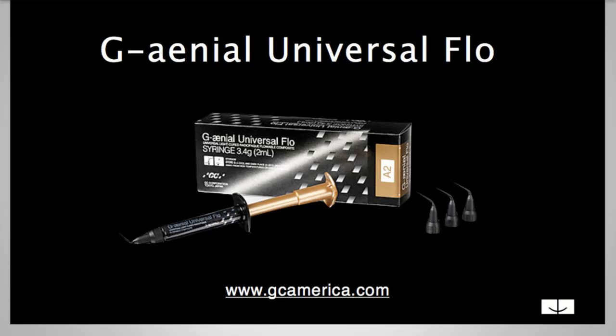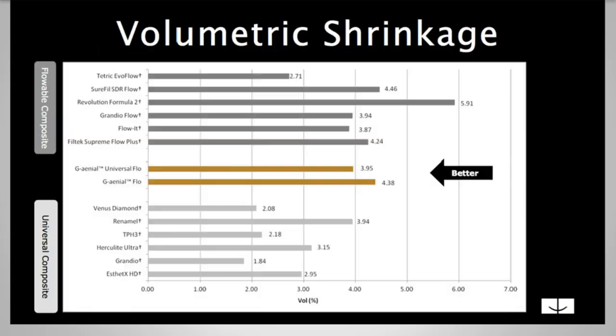So you can see here that the volumetric shrinkage of G-aenial Universal Flo isn't a lot different than some of the other flowable composites. But their shrinkage stress is definitely low as well, so that's really good. You want to have something that has a very low shrinkage stress, especially in those areas around the box and the occlusal surfaces.